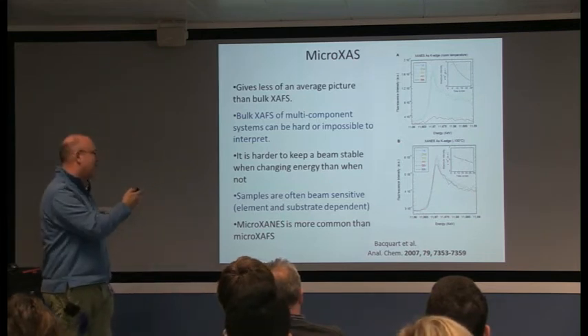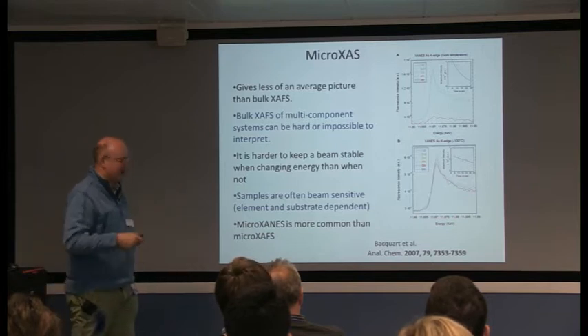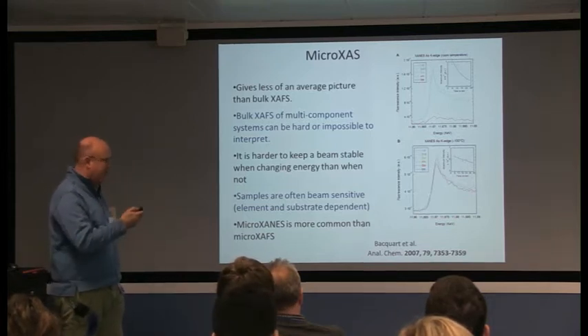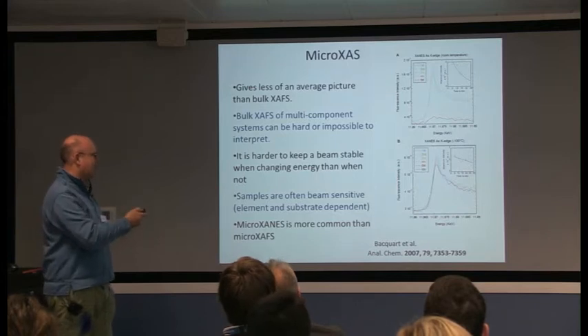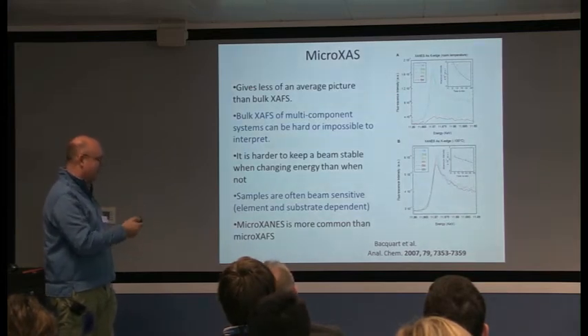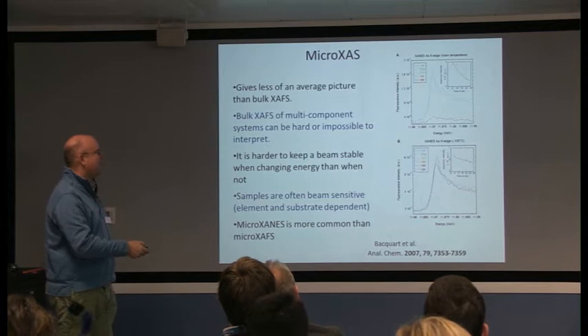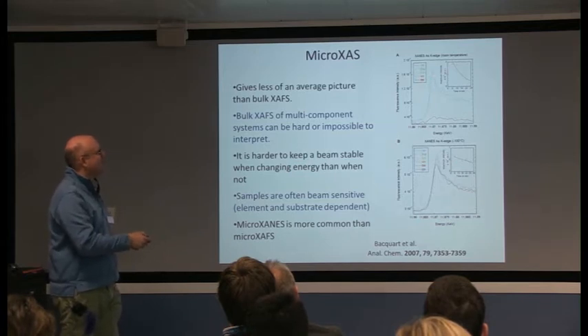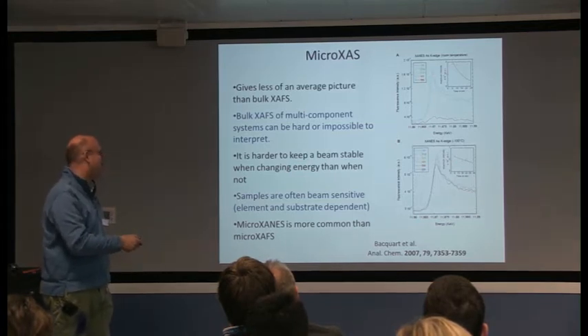This is just an example that cooling does help. We do have a cryostat, though not for use with diffraction on I-18. So at minus 100, arsenic stays much the same as at room temperature. It doesn't stay much the same in an organic matrix.